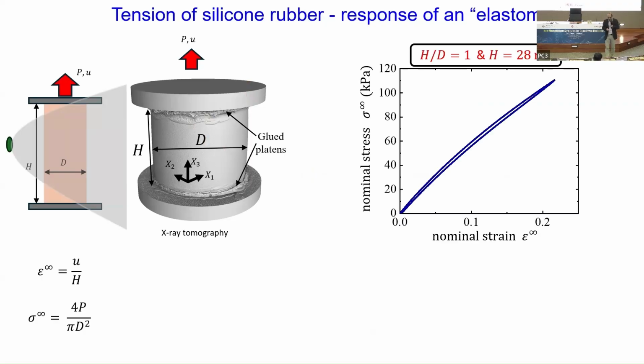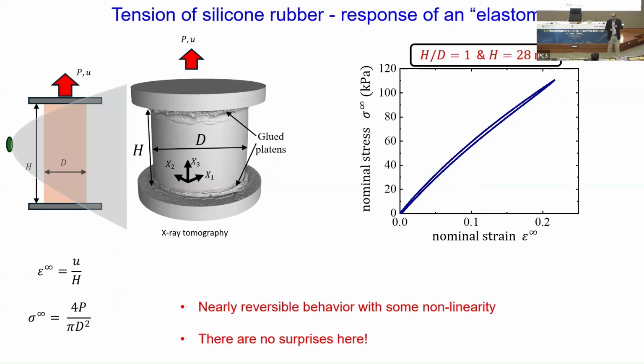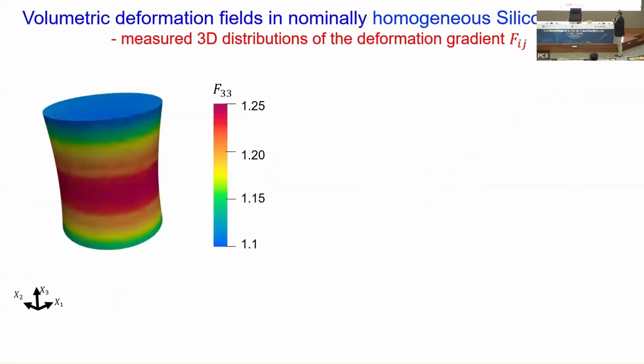It's not really stress-strain. It's sort of load-displacement, because the strain that we're defining is just the displacement divided by the height of the specimen, and the stress is just the load divided by the cross-sectional area. Nothing at all remarkable, right? You basically get a curve that is nearly linear, a little bit of nonlinearity, and nearly no hysteresis. What you'd expect in a rubber, basically.